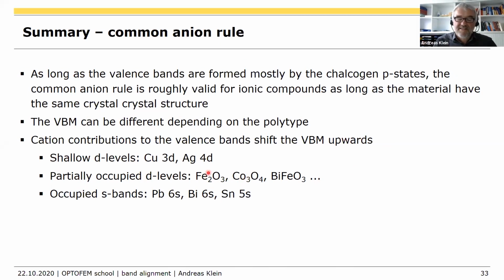In principle, all of these transition metal oxides, all of these many perovskite materials, lanthanum ferrite and things like that, they all have higher valence band maxima. But also the s bands, not only the 6s, lead and bismuth, also the tin. Tin dioxide is tin 4+, and the 5s is empty. If you go to tin monoxide, SnO, then the 5s orbital is occupied. It's not a very stable compound. It really likes to disproportionate into metallic tin and SnO2, but you can make it. And it's at the moment the best candidate for making a p-type thin film oxide transistor.